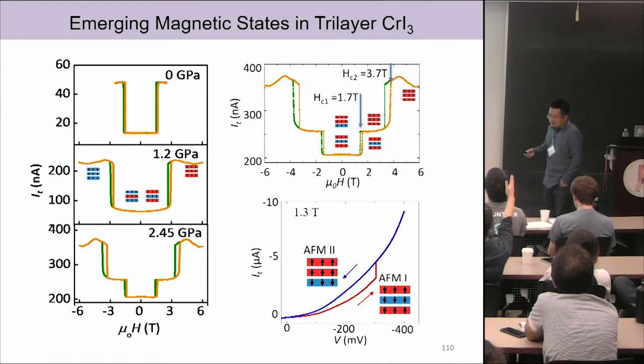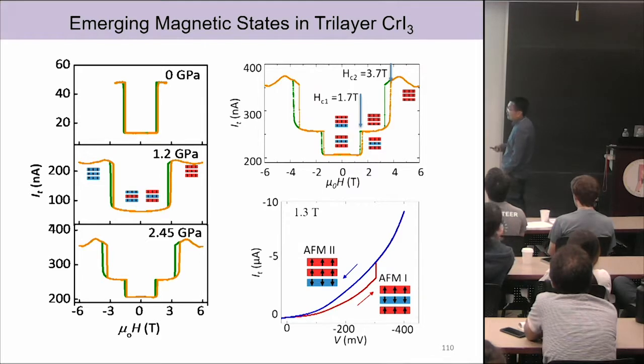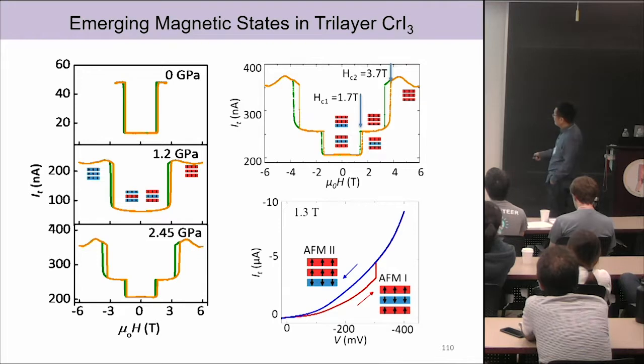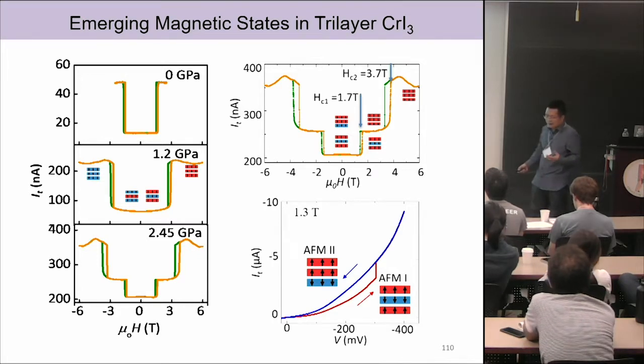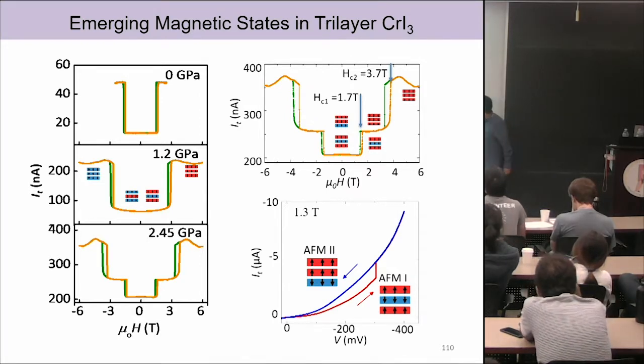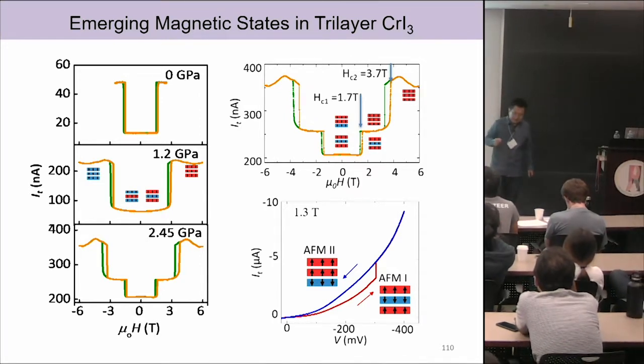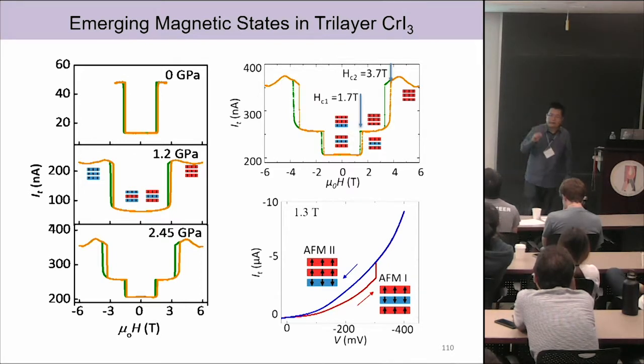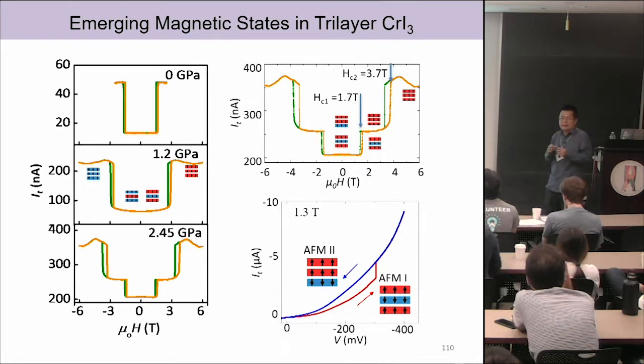Okay, and what's interesting is now we park our magnetic field, and now I scan the bias. Here's what I did. We scan the bias, and we found we can use electric current to flip these two states. First of all, I want to tell you this whole process is non-reversible. It only happens once. So it's also lucky that I have a good student. He takes really careful data, so he didn't miss this. If you just take a bias scan, you basically don't know what's going on.